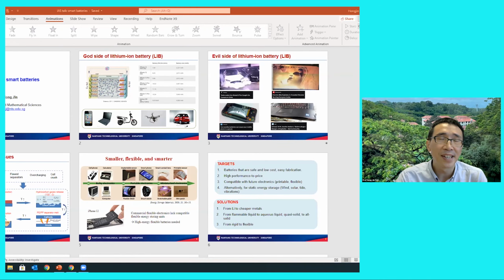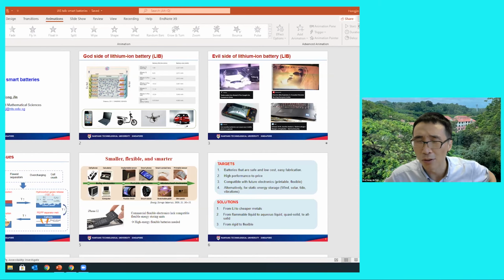And the detailed mechanism of overcharging is that the material becomes unstable if overcharged to a high voltage, or the anode side becomes unstable at a very low voltage. So that's why sometimes people talk about deep discharge, right? Let's say a material has a 100 milliampere-hour per gram capacity, but we're not able to use that capacity fully. We use only 80%, because 100% use of the capacity, which we call deep discharge, also causes hazard.